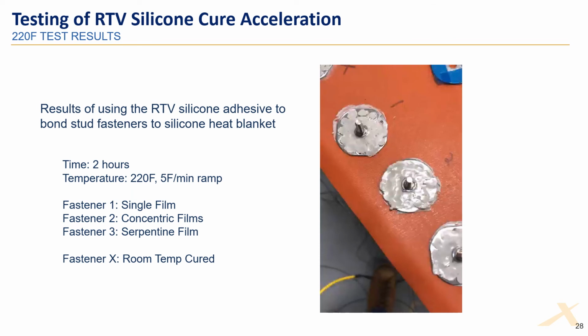Here you'll see a video of the fasteners after the cure cycle is completed. A summary of this particular result was a 2-hour hold at 220 degrees F. We did a 5-degree-per-minute ramp rate for this. You'll notice that the application of the adhesive may have been a bit generous here, but the results speak for themselves.